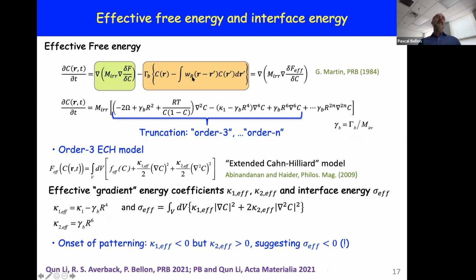We know that what we want is to have this mixing term in orange here, and it's just a balance equation. It's just keeping track of all the B atoms that are located at R and left because of a recoil event, and all the atoms that were B atoms at site R prime that were recoiled into R because of a recoil event. And so we can determine the distribution function by simulations. It's probably what Venkat was saying, and we've seen cases where it's exponential, and somewhere this part of it is Gaussian.